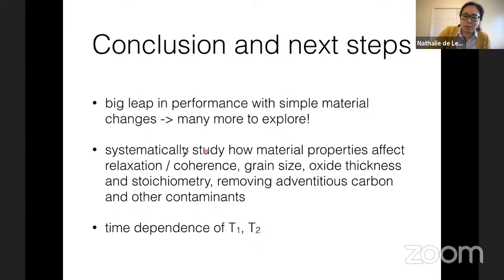But with tantalum, which is very exciting, we're now trying to systematically study how different material properties affect relaxation and coherence and try to get this next factor of 2. The real prize here is that if we can get to a T1 of about a millisecond, then you could do things like break-even quantum error correction, which would be really exciting.